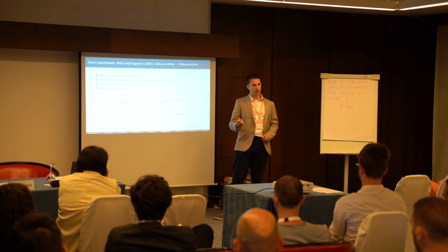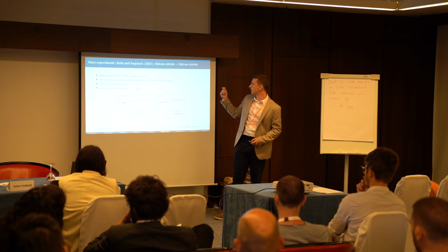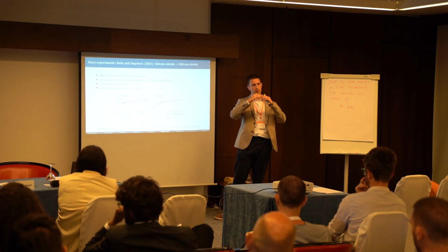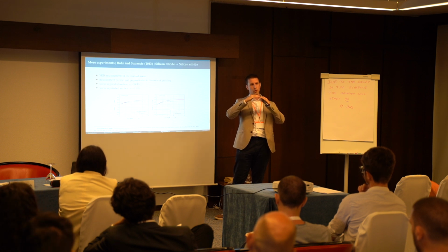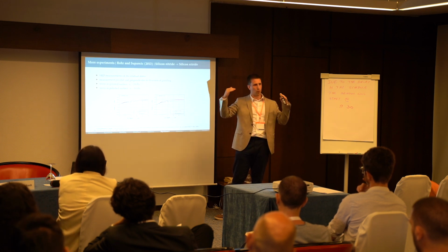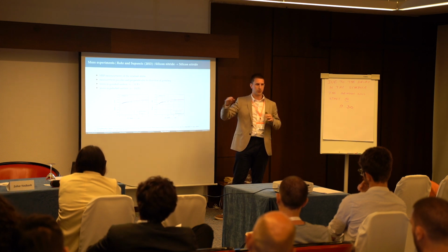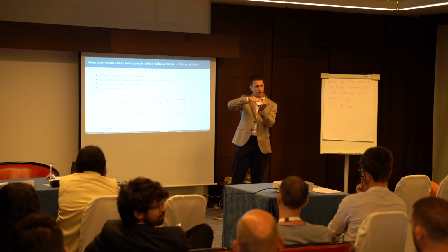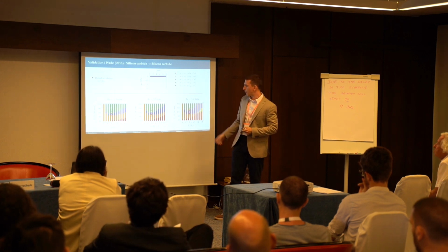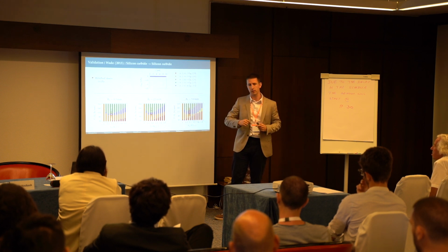Then we found the measurement of residual stresses at the surface, and in the case of silicon nitride, the surface experiences approximately 1 to 3 gigapascals of compressive residual stresses, but that stress decays very rapidly, approximately in the first or second layer, due to the polishing and the forming of the grains. However, in this case, it's very significant, and we need to include it.